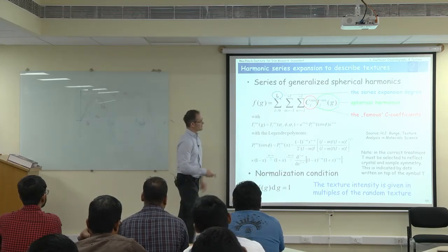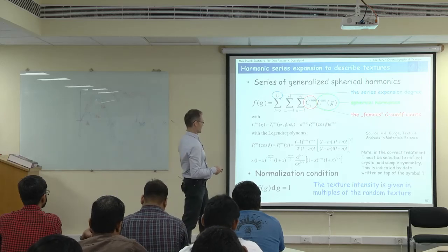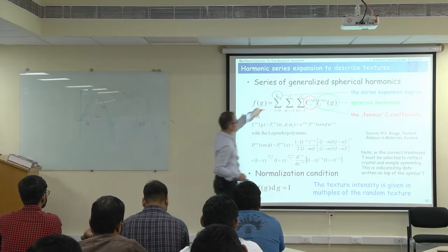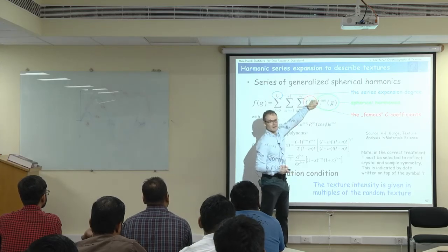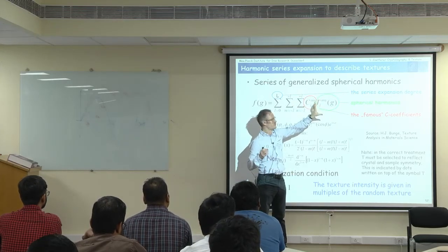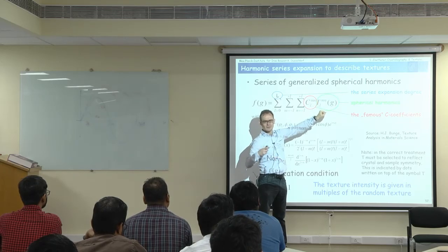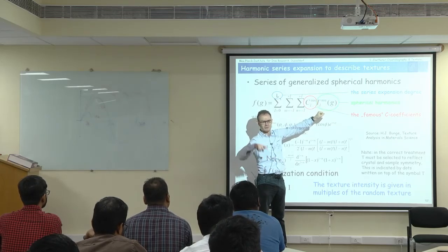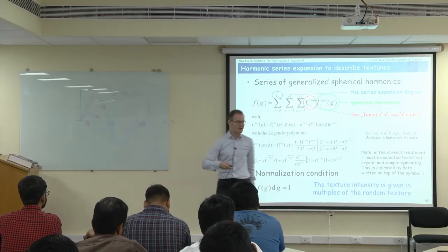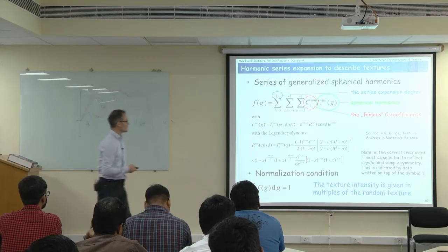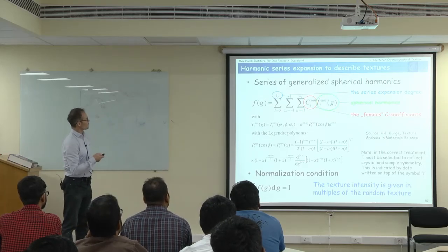I don't know exactly how, but you need to indicate, and that is not shown in this case, but in the case later, you usually indicate here with some dots which kind of T function you mean. Do you mean one for cubic crystal symmetry, for hexagonal crystal symmetry, for orthotropic sample symmetry, and so on? Every time you have a different set of polynomials.